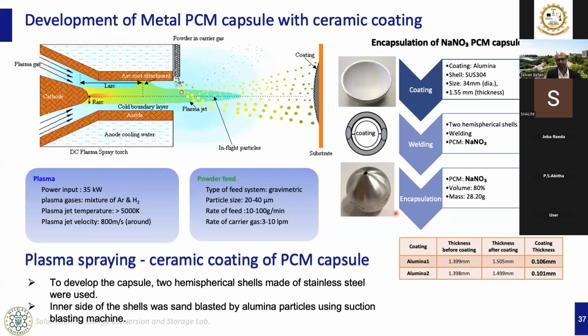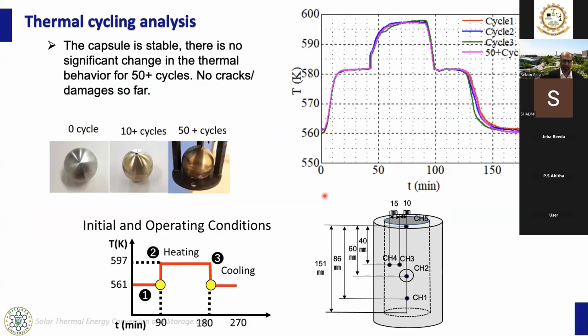And here in this table you can see the alumina coating thickness and details, and the other concept is the same. So we tested this capsule for a latent heat storage tank using sodium nitrate as the phase change material. And then we did the thermal cycling tests. As you can see, we did more than 50 cycles.